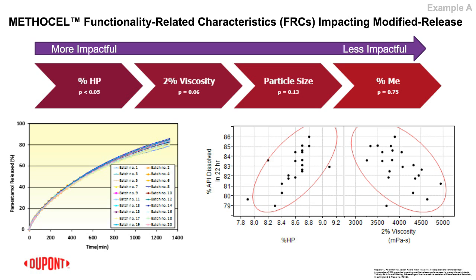And then when you break it down and look at one of the time points at 22 hours, for example, the percent dissolved at 22 hours, and you look at that against those two most statistically significant factors, hydroxypropyl substitution and viscosity. On the right-hand side, there's two graphs, right? So that first graph A on the right-hand side, that's drug release at 22 hours versus HP, and then that B graph on the right-hand side is drug release at 22 hours versus 2% viscosity.